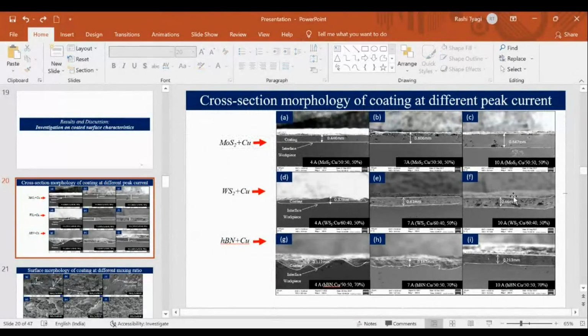Similarly, figures D to F show the WS2 plus copper coating, and G to I show the hBN plus copper coating. In this coating, you can observe that as the peak current increases from 4 ampere to 7 ampere to 10 ampere, a higher coating thickness is obtained. See, this coating thickness changes from 0.446 to 0.647. When the thickness increases, a high current goes through the electrode that helps in more melting of the surface. So a high thickness is obtained in this coating.